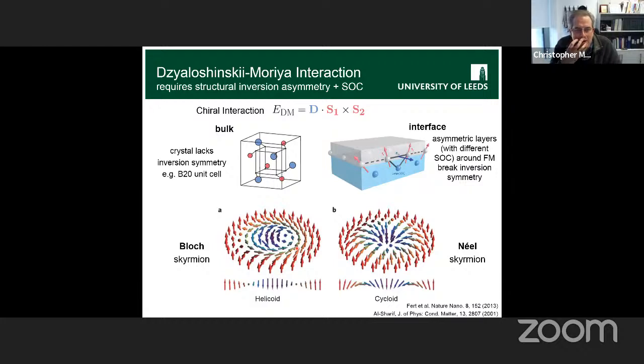So a new kind of twist, if you'll pardon the pun, on magnetism that came along with this was this idea of the Dzyaloshinskii-Moriya interaction. This is quite a mouthful, so we tend to call it DMI. And it's a chiral interaction. So normally in magnetism, we think of Heisenberg exchange, and we have 2 spins and we have the dot product between them. That gives us collinear states like ferromagnetism.